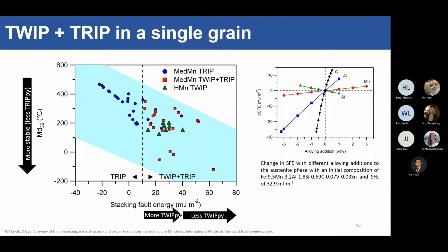And how do we make austenite do this TWIP plus TRIP thing? So we did a literature review, we searched around the literature, and now you can plot little graphs like this. So this is your stacking fault energy, which controls the TWIPpiness, the propensity to twin. And this is your MD30 temperature. So if it's decreasing, you're more stable, less likely to form martensite. And very conveniently, when you're at 10 millijoules per meter squared here, anything more than that, you actually start to activate the TWIP effect.